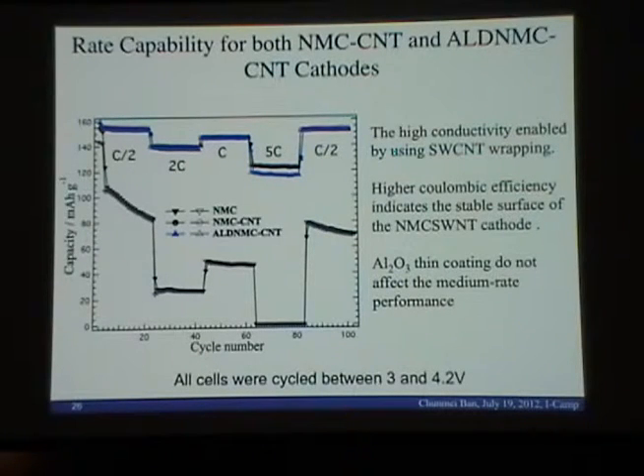And all of the testing, we test in the coin cell configuration, just like a button cell. We use the active material mixed with the binder and the carbon additives, make this electrode and test it in the coin cell configuration. And on this carbon nanotube one, we didn't use any polymer binder, because the carbon nanotube is really long and can wrap all the particles, so we don't need the binder anymore. And this blue and green show that this carbon nanotube enabled electrode has greatly improved rate capability, because they have 120 milliamp hours per gram, even at 5C. Compared to that, there's a lot of capacity lost when we use just the bare material particles.